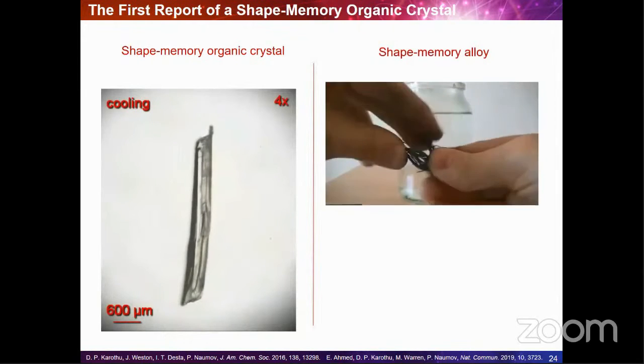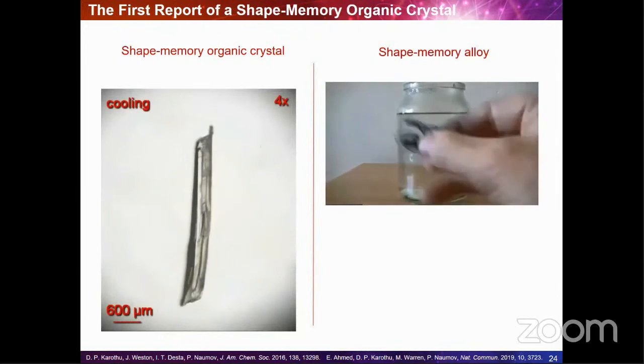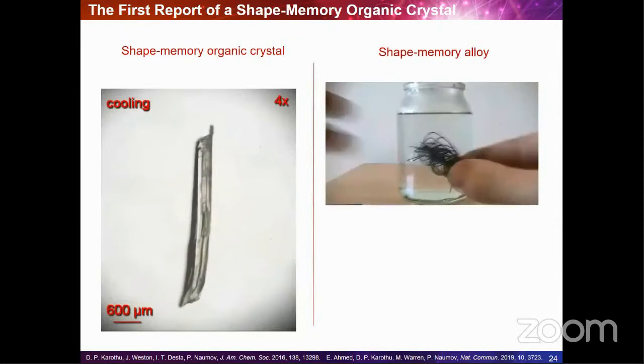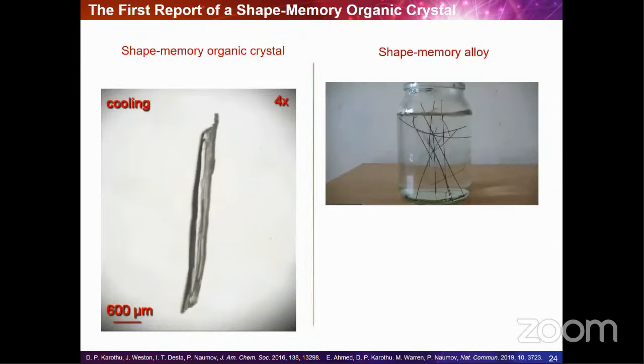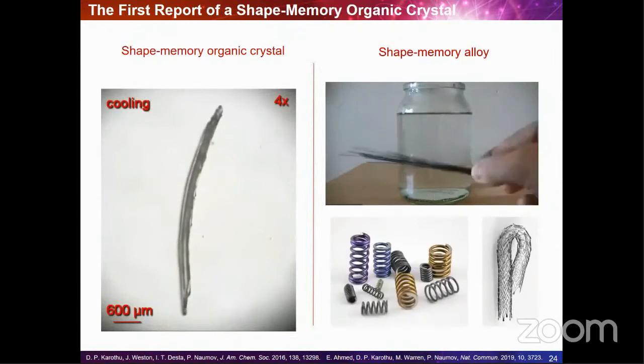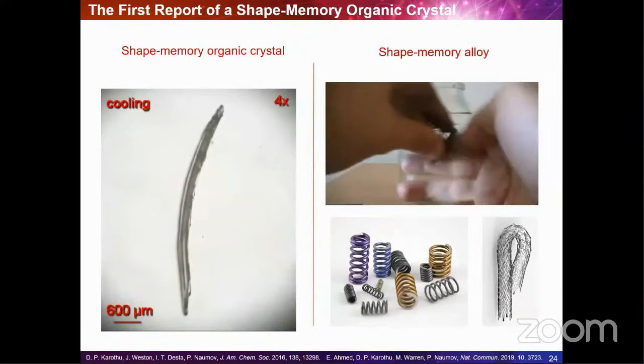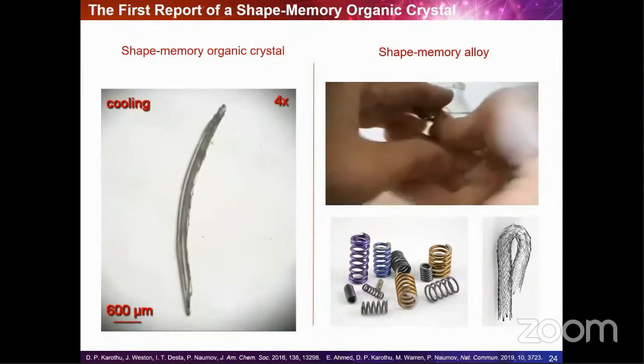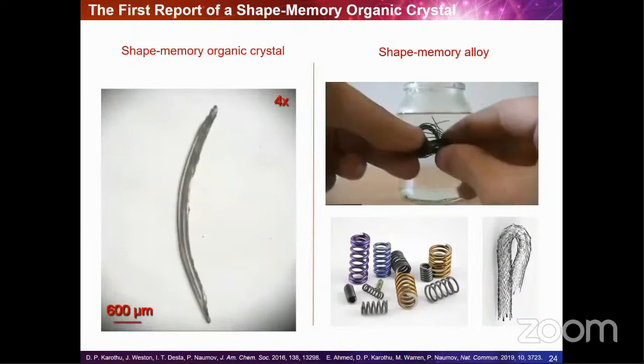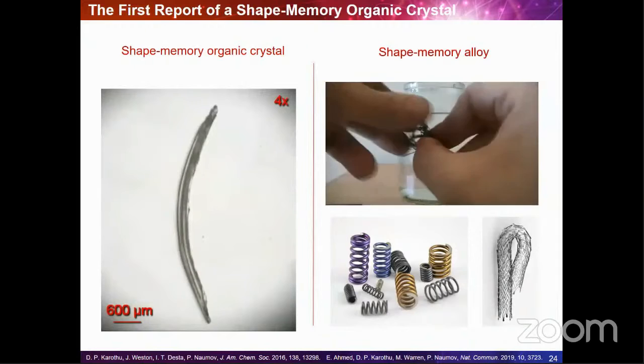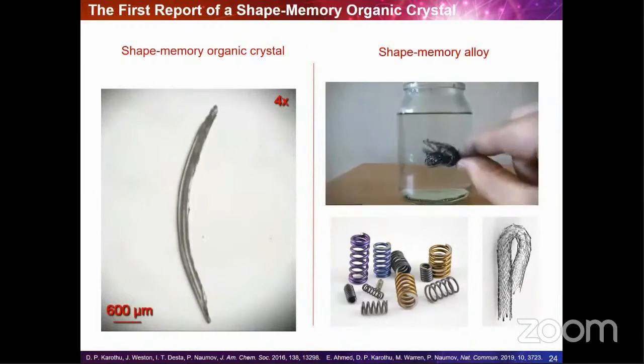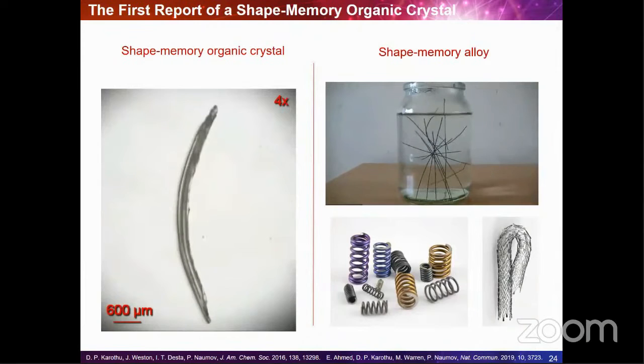Such plastically bent crystal can act as a bimorph, and their phase uniformity can be recovered thermally by taking the crystal over the phase transition temperature. And this recovers the original straight shape, and the crystal can be bent by a reverse thermal treatment, and this results in a shape memory effect, which is similar to those observed with some shape memory metals, as you can see here from the video, or alloys. And these alloys are actually used in medical devices. So somehow the crystal appears to retain the information of the deformation structure. And this transformation between bent and the straight shape of the crystal can be repeated several times by alternative heating and cooling, and we do not see any deterioration of the crystal.